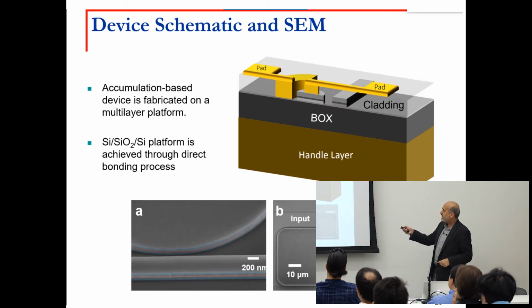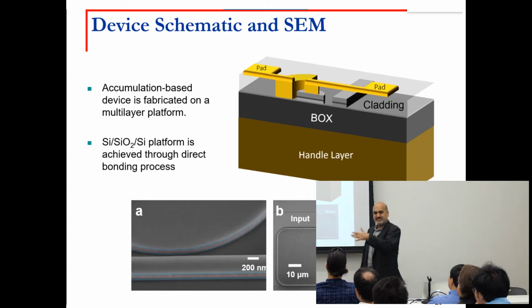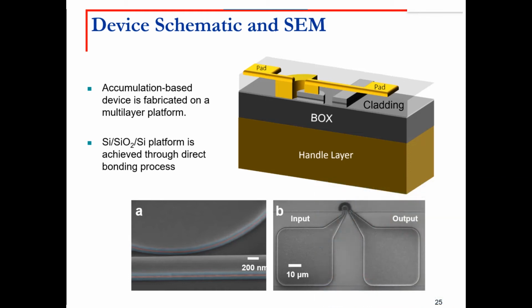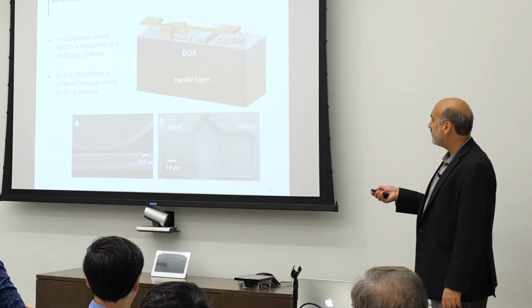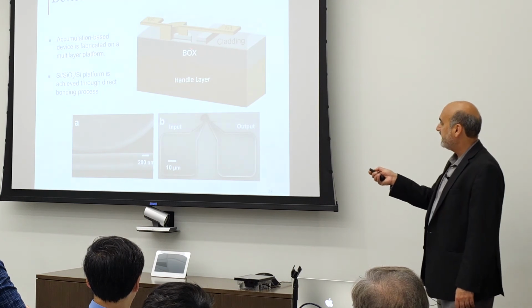So here, the two contacts are placed, one in the middle of the resonator. The electromagnetic field of the mode is usually in the periphery. It doesn't see the center of the disk. So I can safely put one electrode there, and then I will keep my silicon about 30 nanometer or so around the structure as a pedestal. Electromagnetic field doesn't get into that, so I will put my second contact there. This way, I make sure that the contacts don't add loss. Some of the SEMs are shown over here, waveguide and resonator at the coupling region.